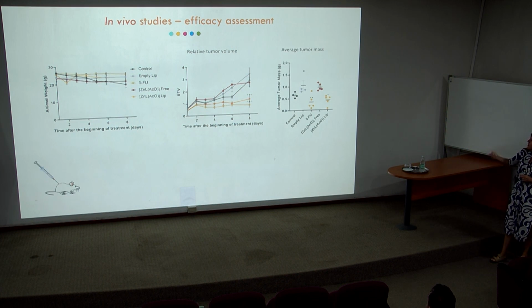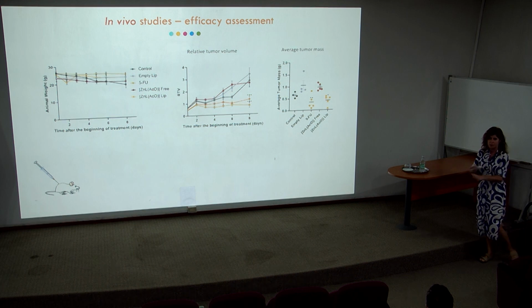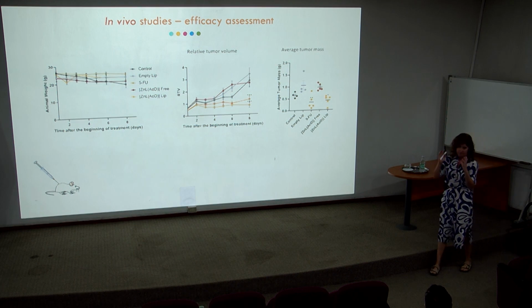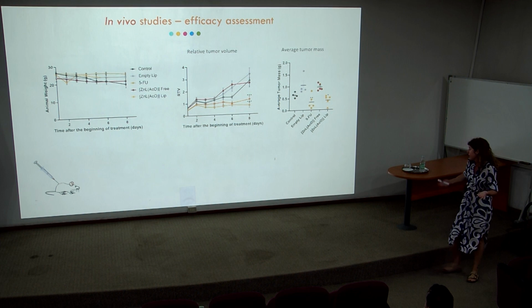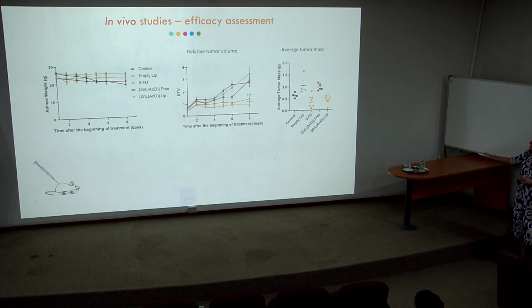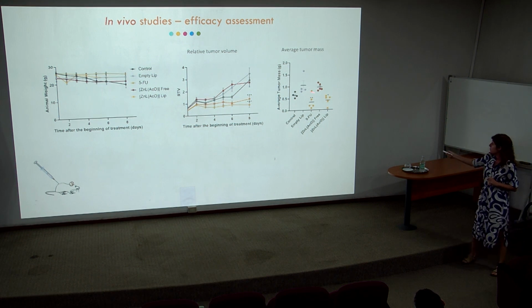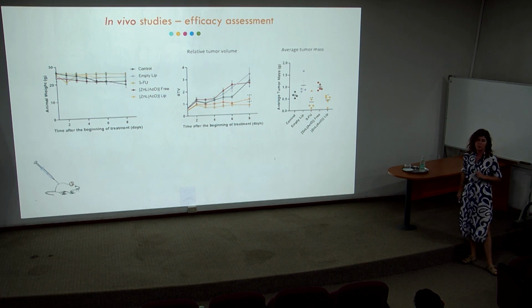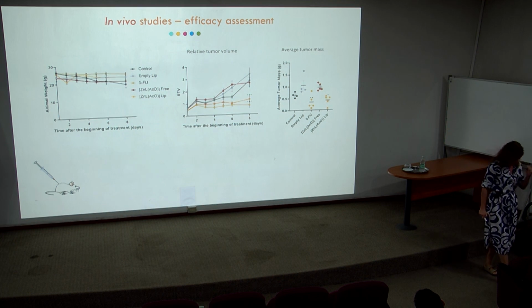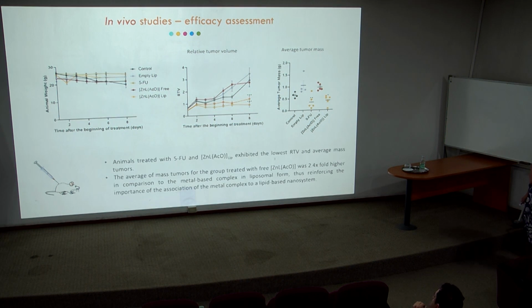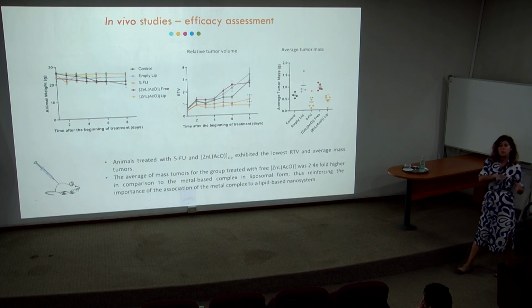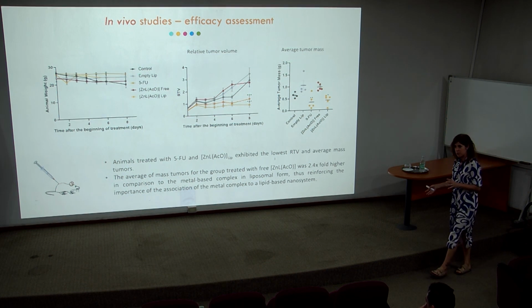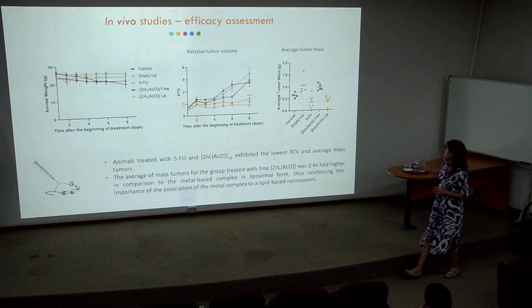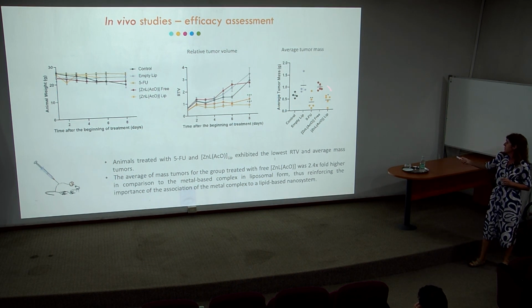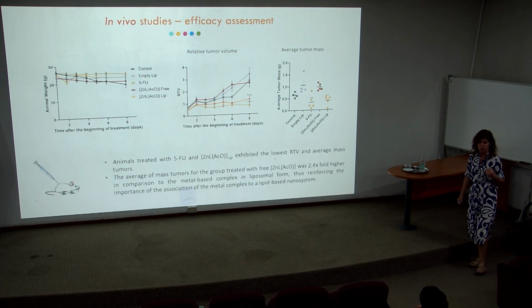In terms of average tumor mass, this was after the end of the study when the animals were executed, we can clearly see that the best results, the lower average tumor mass, were found for the positive control and for the liposomal formulation of our compound. So these are very positive results. We could see an effect from incorporating the compound into the liposomal formulation, because the compound is much better in the liposomal formulation than in the free form.